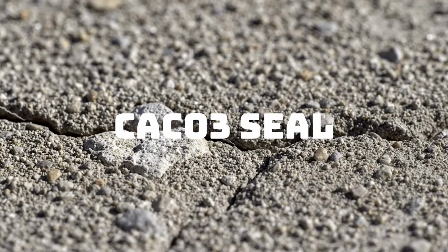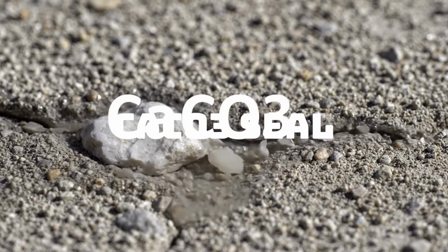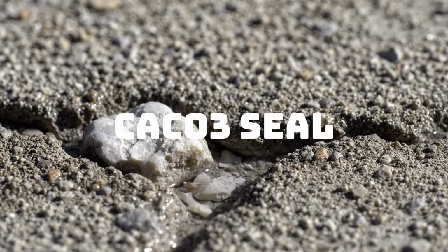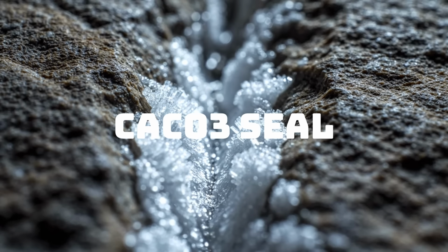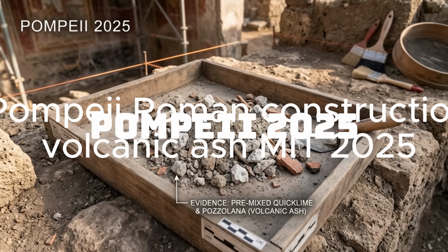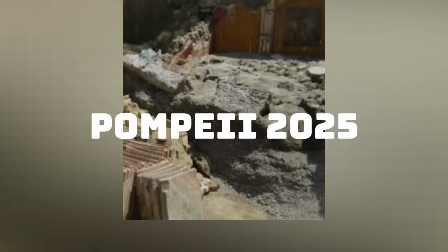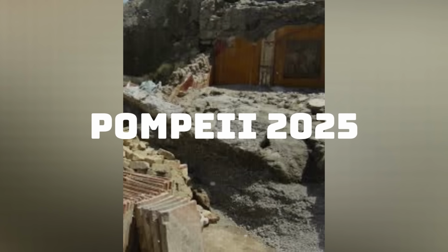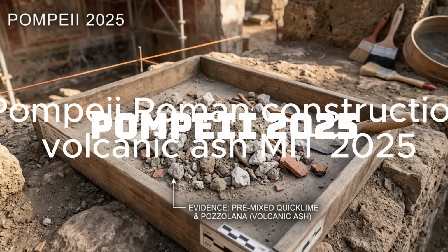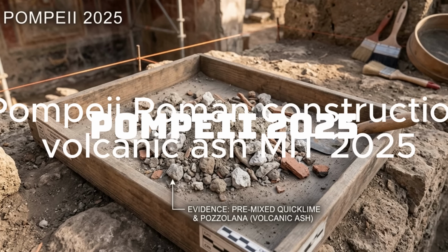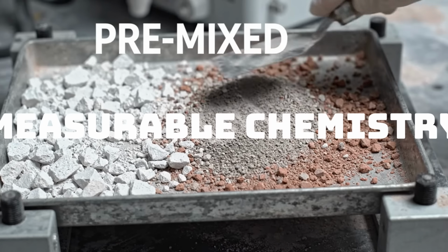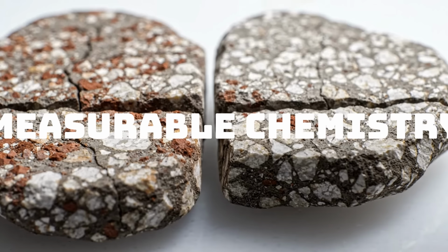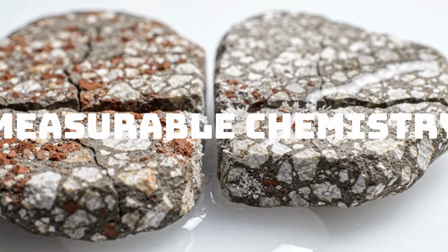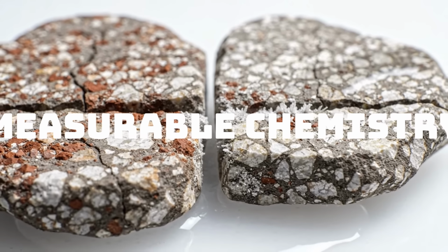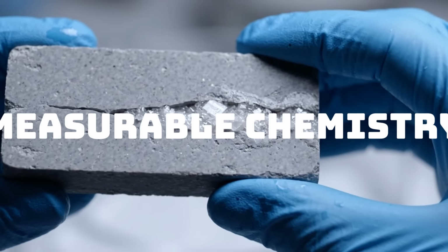Then, when a microscopic crack later opened in the concrete and water seeped in, the water dissolved calcium from the nearest lime clast and carried it into the crack, where it precipitated out as fresh calcium carbonate, sealing the crack with newly formed crystalline rock. In a 2025 follow-up, the same MIT team examined raw material piles preserved at an active Roman construction site, frozen in time by the Vesuvius eruption at Pompeii. They confirmed it. Intact quicklime fragments were pre-mixed with volcanic ash before water was added. Exactly the hot mixing protocol the chemistry predicted. The walls heal themselves, not as poetry, but as measurable, peer-reviewed chemistry, replicated in modern lab samples that scientists have cracked, run water through, and watched seal themselves shut.